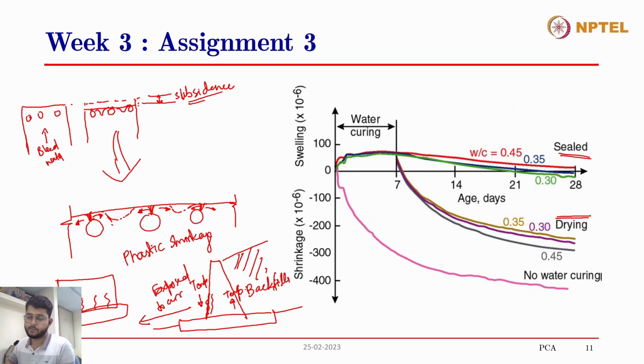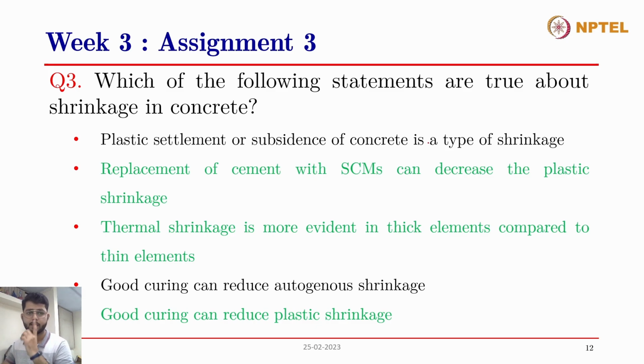But when compared with the sealed specimens, where the concrete elements are not exposed to any kind of drying, the water inside the concrete is intact, and we are also providing curing water from outside, we can see that almost all of the shrinkage is getting compensated by the swelling, and therefore at 28 days there is almost no dimensional change in the concrete elements. So this is the effect of water curing on the shrinkage. Due to the swelling, it compensates for some of the plastic or the other shrinkage that is happening inside the concrete.